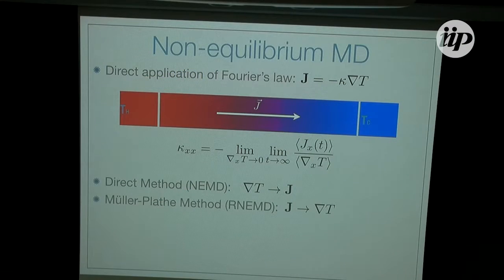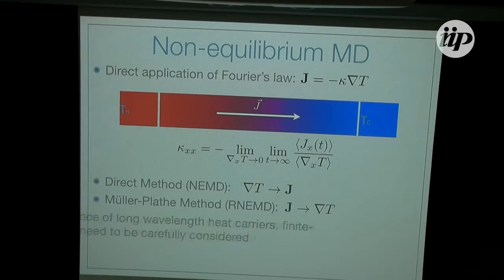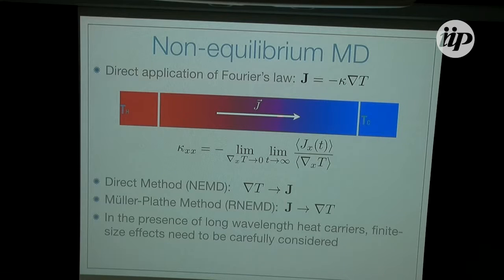It's completely unphysical, but it works beautifully, as I'm going to show. Now, once I have a stable or steady state heat flux, I can calculate the temperature gradient numerically on my system, and I can calculate the thermal conductivity, or at least that component of the thermal conductivity tensor. This limits me a little bit, since I have to calculate each component individually, but it's still good enough.